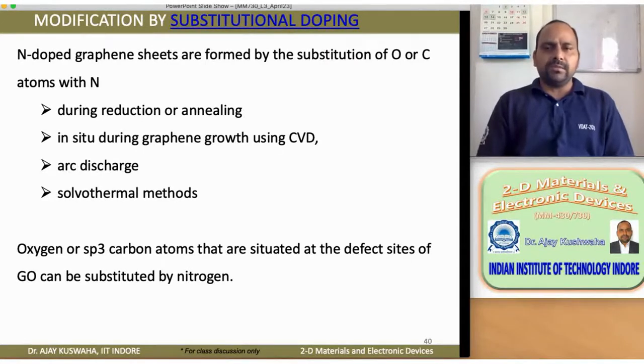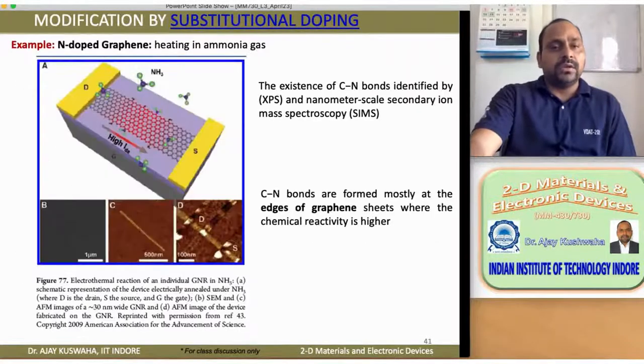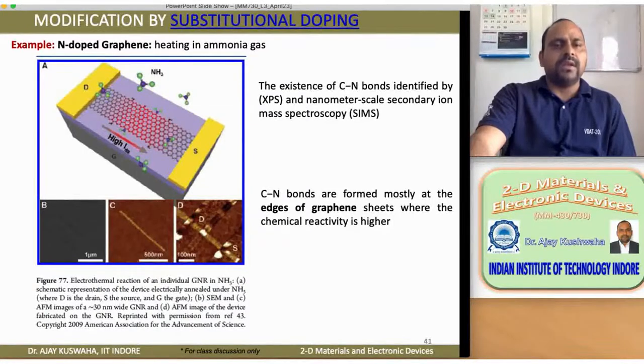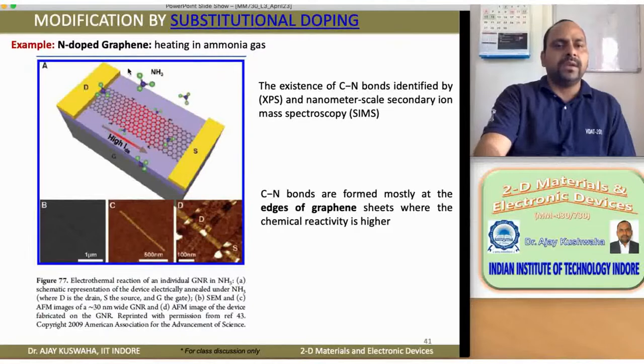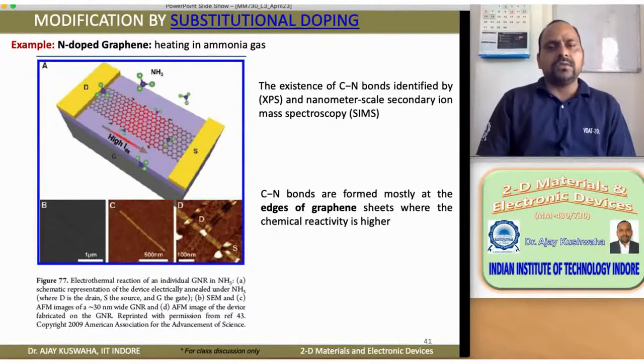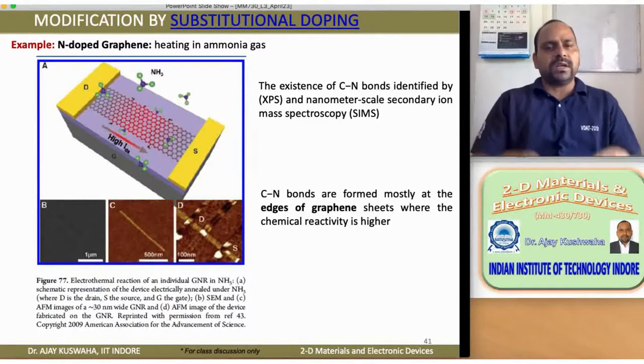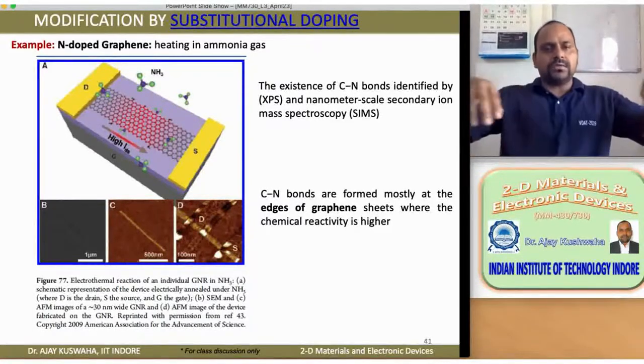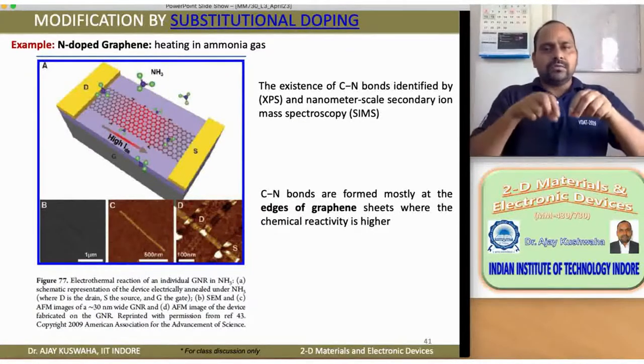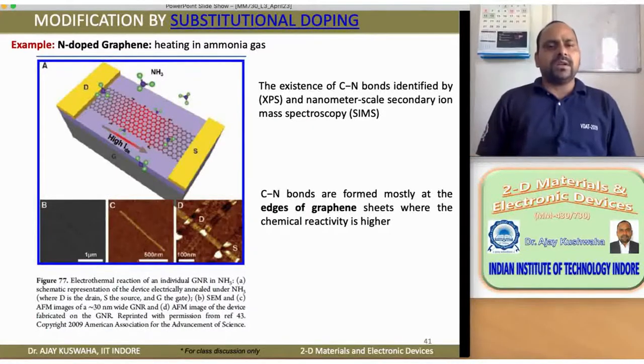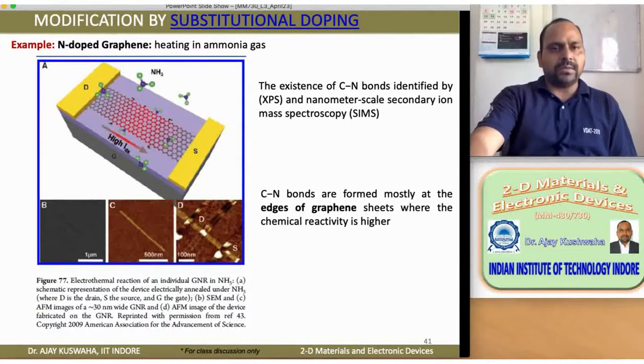So a variety of different techniques can be utilized to achieve nitrogen doping. Oxygen or sp3 carbon atoms that are situated at the defect site of GO can be substituted by nitrogen. Okay. Here is one report in which a nitrogen-doped graphene based FET has been demonstrated, and this graphene doping is achieved just by heating the graphene in ammonia gas. They said that the existence of the CN bond was identified by XPS and nanometer-scale secondary ion mass spectroscopy. They also observed that most of the CN bonds appear at the edge, since this is a kind of ribbon, and the edge is more defective, so it dominates this kind of interaction. Then they investigated how the property of the FET changes once it is modified with nitrogen.